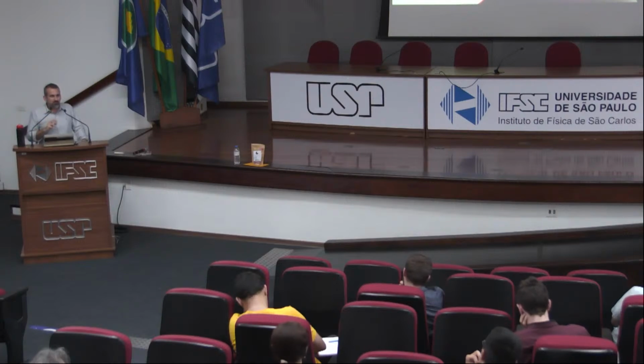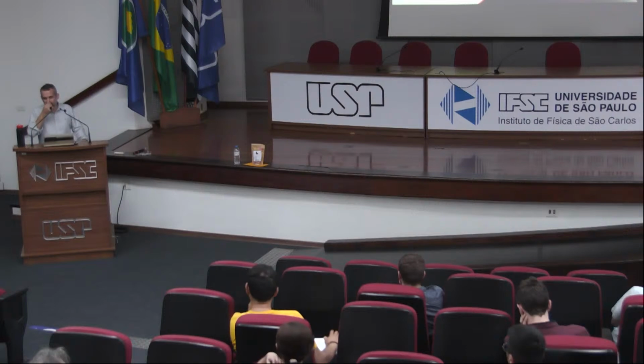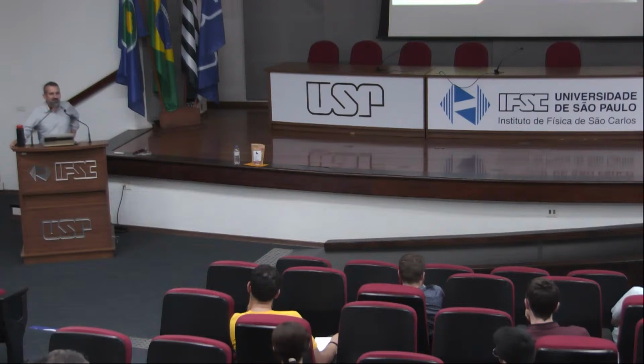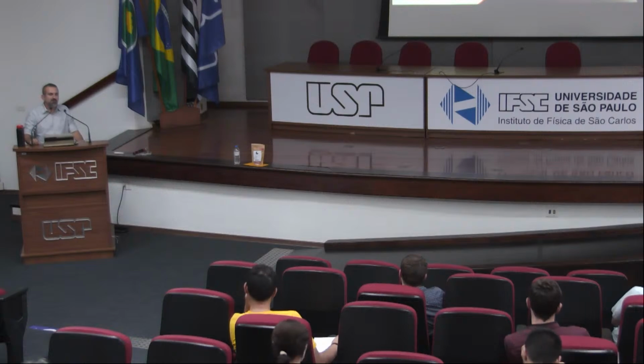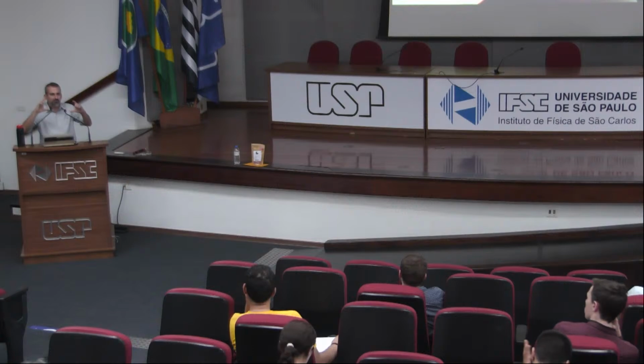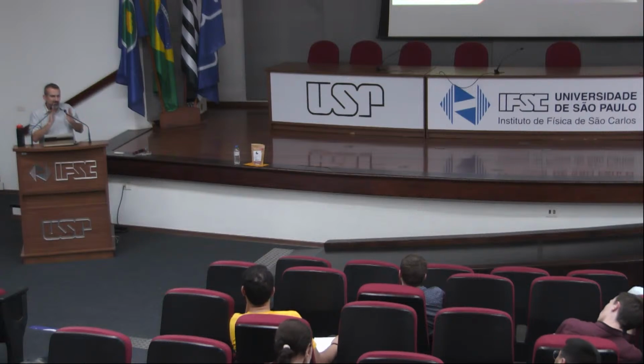When you go to electronic properties, you have to take a little bit of care. For instance, the band gap of the material is usually underestimated with the kind of simulations that we do. And when you look at refractive index, for instance, you have to apply some kind of correction to be able to compare it to experiment. But even with this limitation, you can still learn a lot, because the absolute value of the band gap is not very good, but the shapes are good. Usually the peaks are just a little bit shifted, but you can get all the peaks that you want for optical properties, for instance. So in principle, electronic structures are a little bit tricky, but you can still learn a lot from them. And there are new functionals, but then it's more expensive.